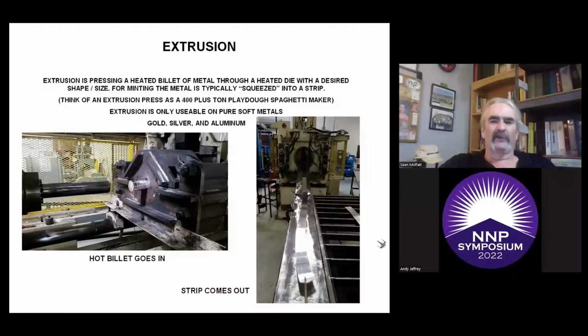Extrusion is only usable on pure soft metals like your gold and your silver and your aluminum. Now, your coppers and nickels, they're too hard. They would work harden and you wouldn't be able to squeeze. So the whole process works like this. You take a heated billet of metal. This one here is a pure silver billet, and you put it into a heated container. Then you have this big rod right here. It's called a stem, and you push that billet in there, and it's up against the die, which is in the front part of the machine. And then you apply your hundreds of tons worth of pressure, and then it's squeezed out.